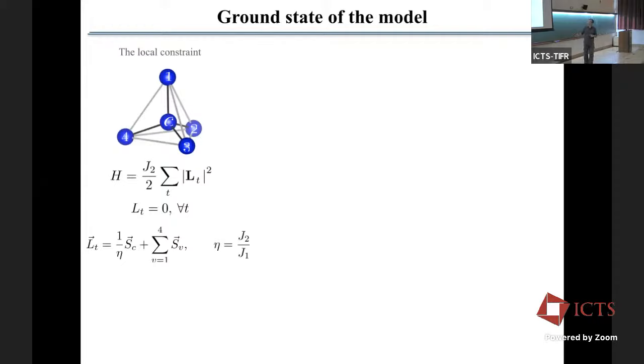Now, the only difference is that in Pyrochlore system, you will have only this term of the 4 spins. So the 4 corner spins will give you the magnetization of the tetrahedron, and that's all you will have in this term. But now, we also have this central spin here, the green one in the middle, that gives an additional term divided by eta, which means that when eta is very small, this term here will dominate. And since the Hamiltonian is a sum of this term squared, what we want is to minimize the value of this term, ideally to have it equal to 0. We'll see that it's possible for the spin liquid regime, but not for small value of eta.